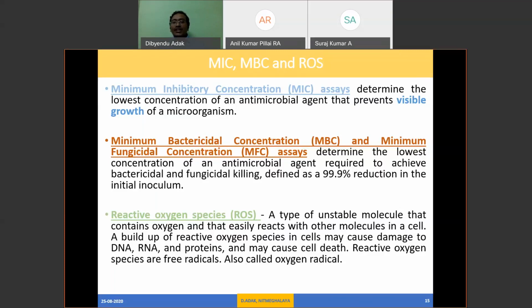MIC is the minimum dose of the antibacterial agent which will stop the growth of your bacteria. That means they will not be able to increase their family. They will be stagnant. If the cell content is 10 to the power 6 CFU per ml, and you add antibiotics of maybe 0.1 milligram per liter, and the generation of the bacteria cells is stopped, we can say that the MIC value is 0.1 milligram per liter.